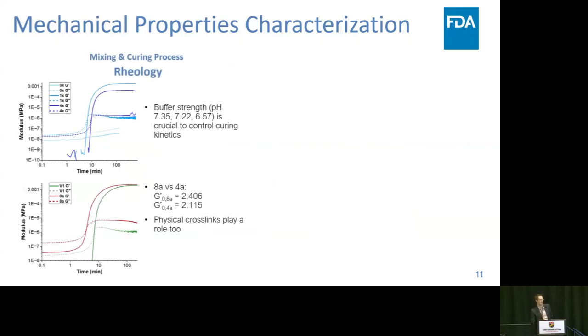So from here, we wanted to evaluate the mixing process and curing. And so using rheology on the pre-cured mixtures, as well as the mixture as it's gelling, you can look at the effects of buffer strength and discern the control over pH that's needed and what is crucial to control the curing kinetics, as well as giving you the ample enough window of mixing time that you need to manufacture this. You can look at the differences in the 4-arm and the 8-arm polymers, and you can see that these are relatively similar storage modulus, which is an interesting observation that we made here. And it points to the fact that there's physical cross-linking to consider, as well as geometric constraints and how the polymer molecules actually can all fit in space.